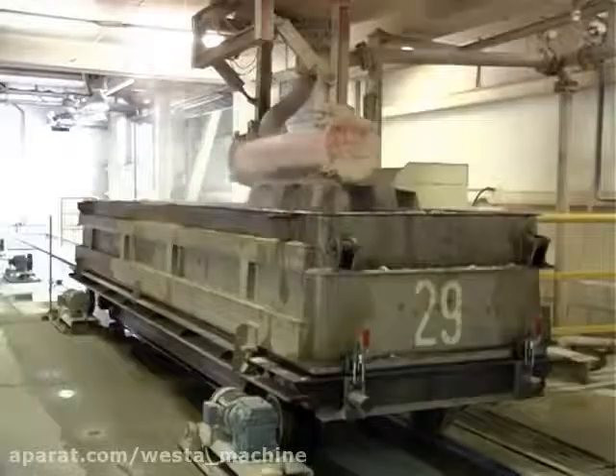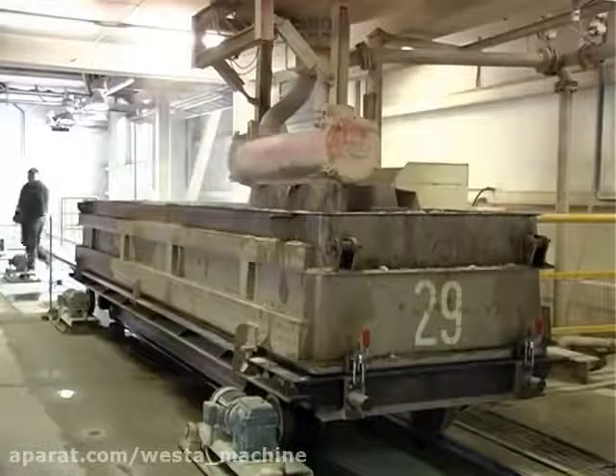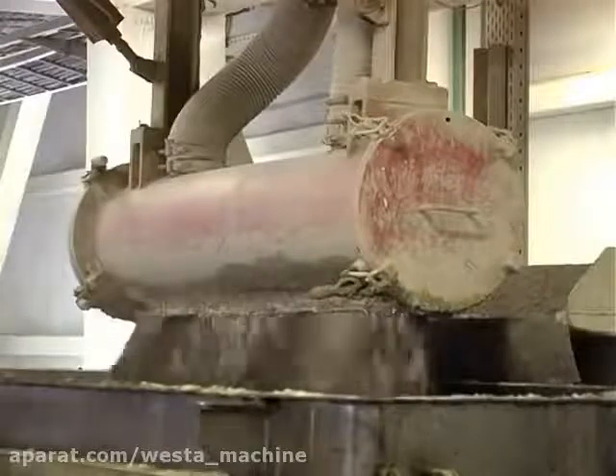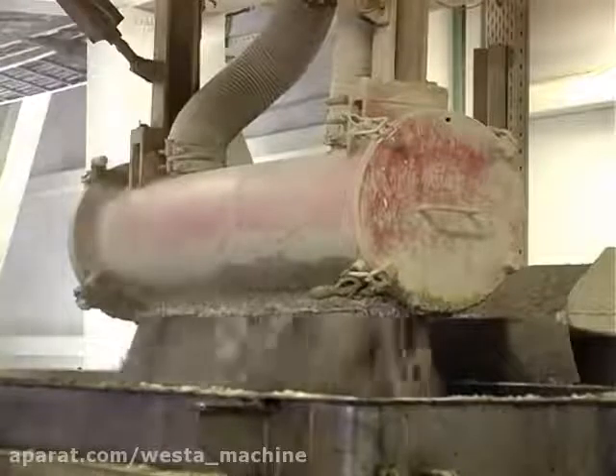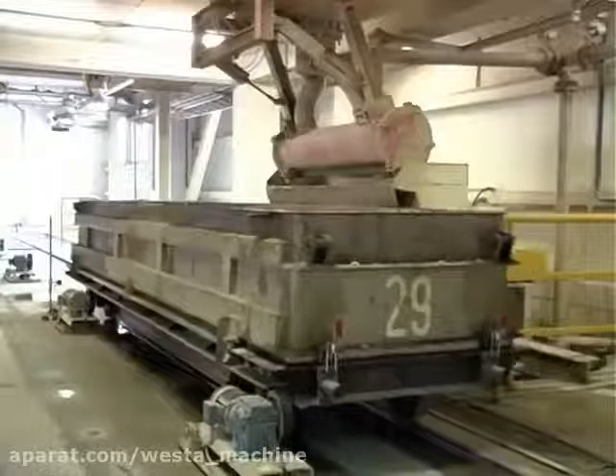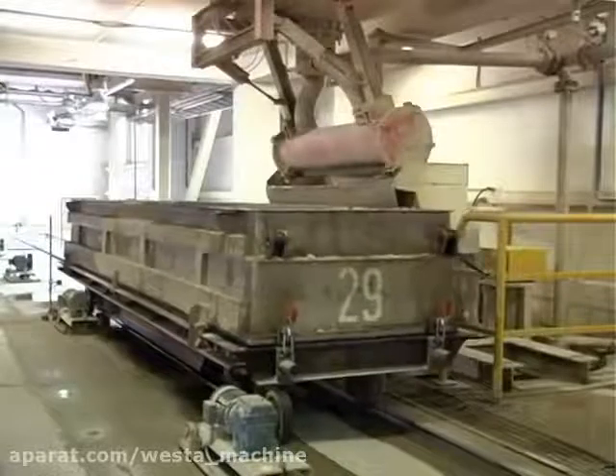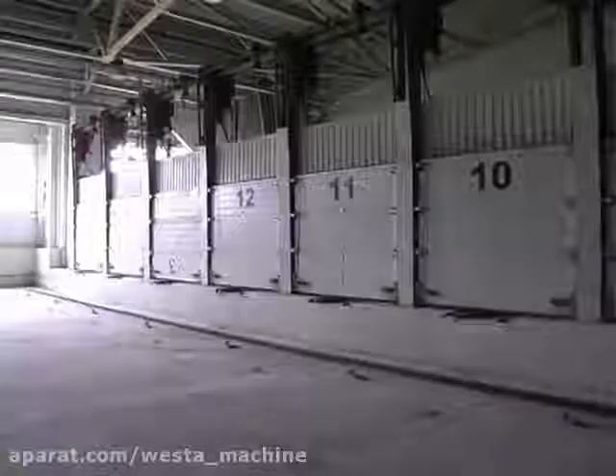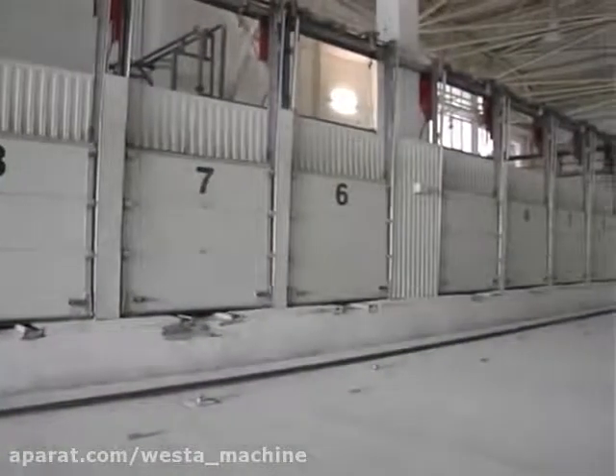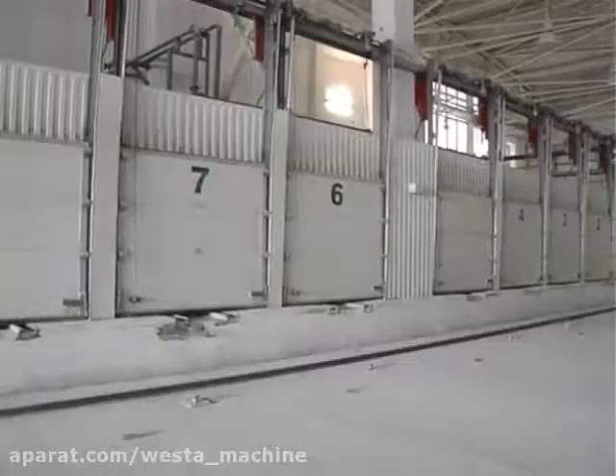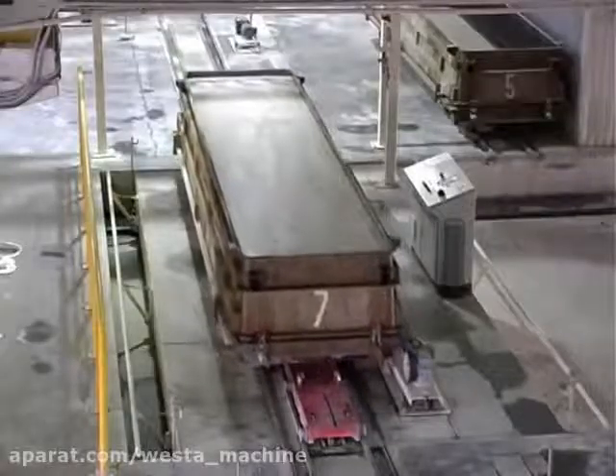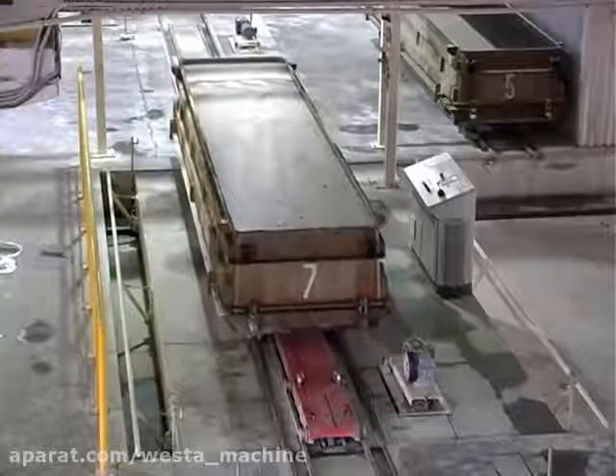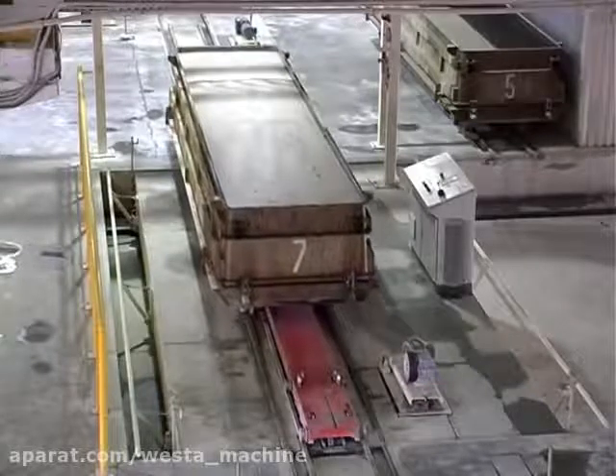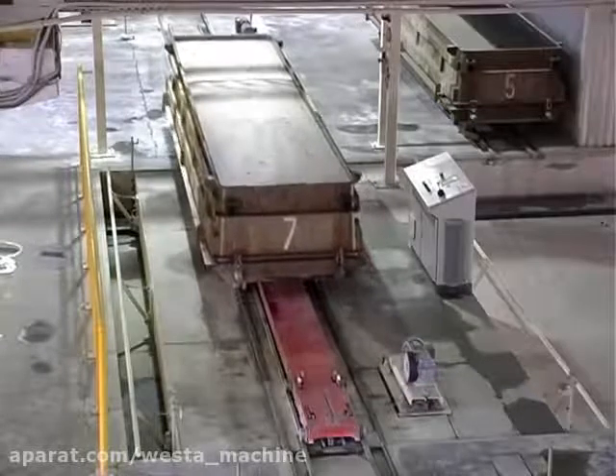A definite quantity of autoclaved aerated concrete mixture is poured from the mixer in a casting mold which is already oiled. Hardening of mass happens at precisely defined temperature conditions in a heated chamber during 2.5–3 hours in order to stiffen and increase the volume. Thus, autoclaved aerated concrete consists of 80% air and only 20% solid particles.